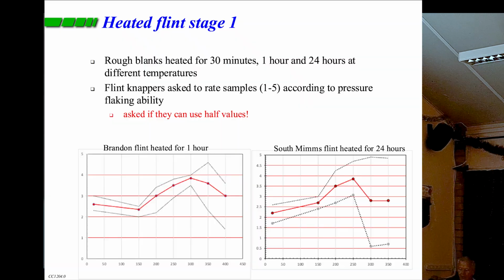And the first stage of the experiments is our flint knappers carved out rough material, rough flakes, rather like this one. They just knap around the edges and we use those as the preforms. And then what we did is heat them up for